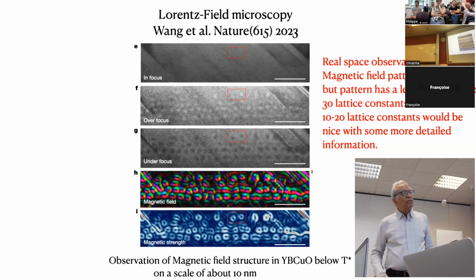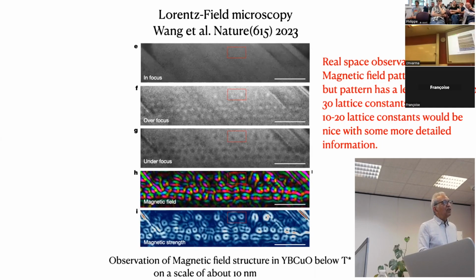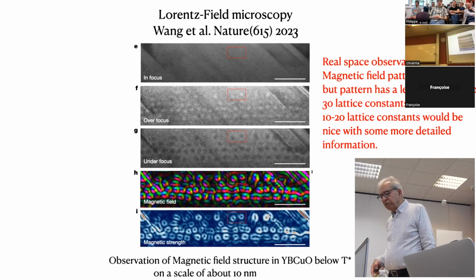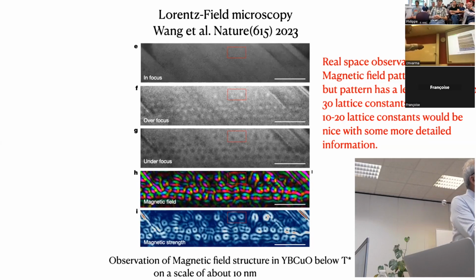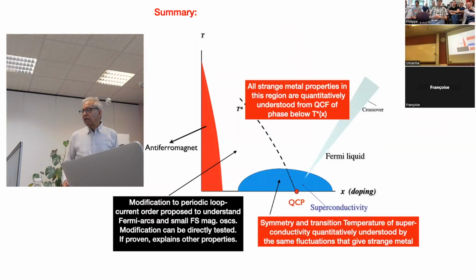Okay? But the fact that there is a real space observation of the magnetic field pattern is nice, but I thought it was 30 lattice constants. It's more like, Philip informed me, 50 lattice constants, while 10 to 20 lattice constants would have been better. Okay? And I don't understand the details of it. It's only the in-plane field pattern. There should be some out-of-plane field also, but they should change their scattering geometry so that it cancels the perpendicular. So this is the state of the art. Again, done in wonderful China.